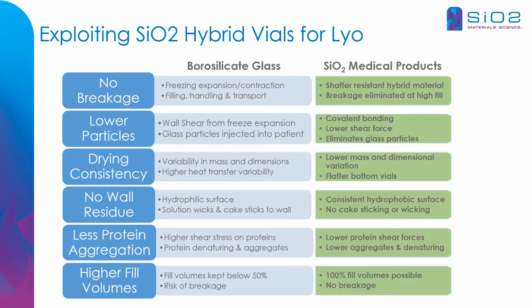One of the things in lyo is hang up on the wall of the container, residual material that gets lyophilized. Because we have a hydrophobic surface, the liquid drains down into the bottom of the container, and you get a lyo cake without a lot of fogging or wall hang up. Also, another thing we found is less protein aggregation, and we have a case study to show you on that.